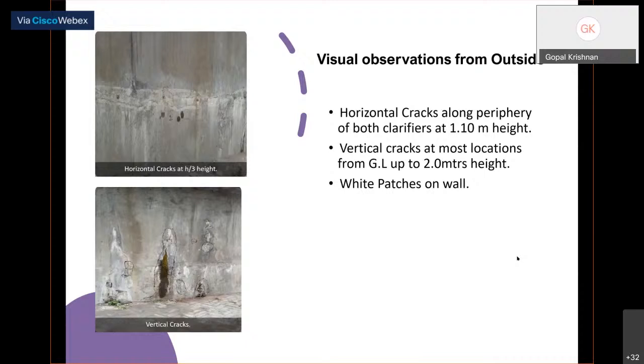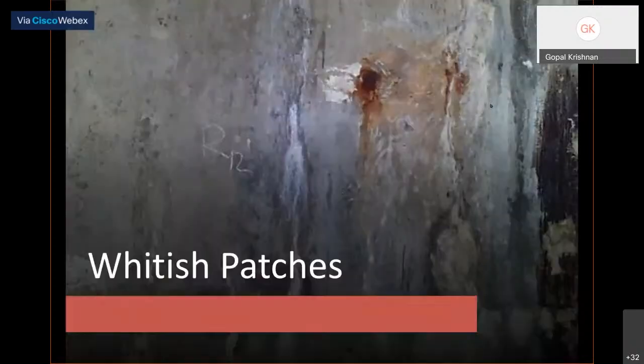Okay, the main problem: horizontal cracks in the periphery at about 1.1 meter height, and vertical cracks in most locations at a 2 meter level, as you can see on the left-hand side. There is leaching out because the water is continuously seeping through the wall, everywhere. You can see the patches here. Here is a close view of the leaching out patches.